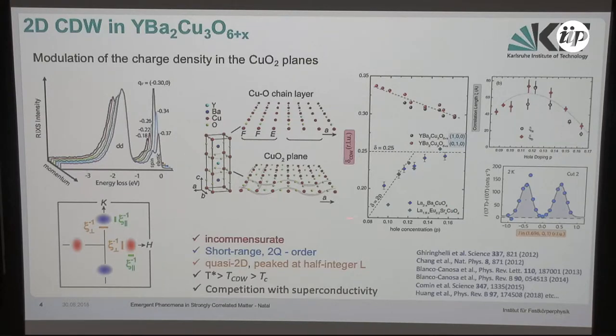And there are other interesting facts. For instance, the incommensurability has a strong doping dependence, which is opposite to that of the stripes. In the case of YBCO, and also in the case of Bi-based and mercury-based compounds, the incommensurability increases as you decrease the doping level and go towards the Mott insulating phase. Whereas in the case of stripes in the 214 cuprates, the incommensurability is known to scale with the doping, at least up to 12%, and then to somewhat saturate.